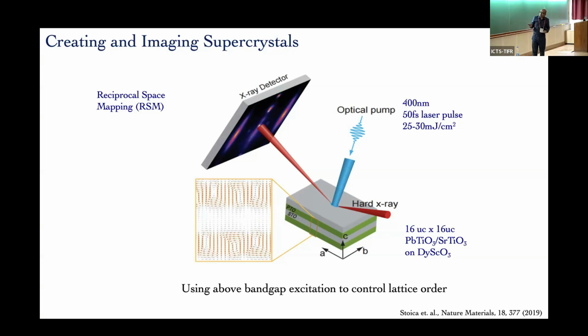Okay, so one way to do that is to optically pump it. So we go above the band gap of lead titanate at 400 nanometers, 50 femtoseconds, and we pack some power. You need a certain threshold to induce enough charges, on the order of about 10 to the 20, 10 to the 21 carriers per centimeter cubed. And you flood these interfaces for a brief period of time, 50, 100 femtoseconds. So you're sort of taking a pack of charge and seeing what this does, right?